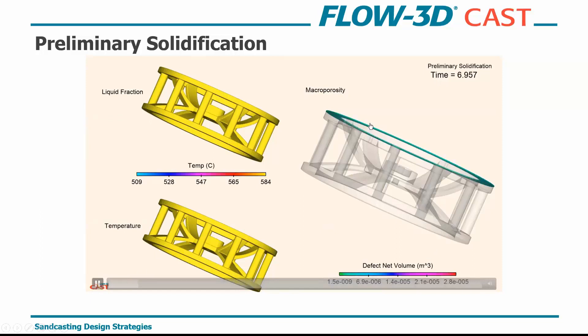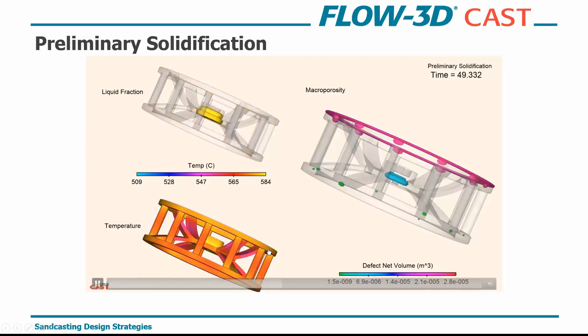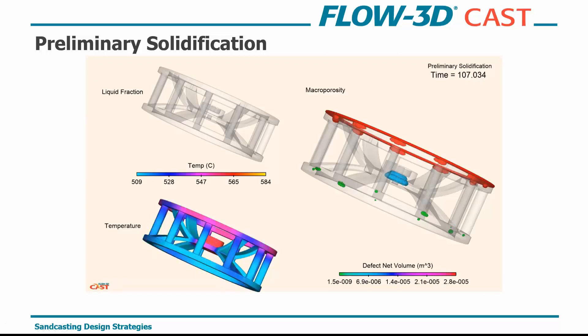We see a drop initially due to gravity, which is usually solved when we add rigging. Thin sections solidify first — out to the rim and into the hub. We're seeing some porosity prediction at the junctions of the spokes and in the main hub. From here, the casting engineer can start developing ideas on how to neutralize and eliminate these problem areas.